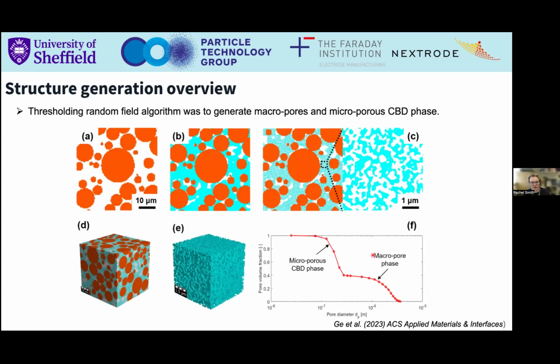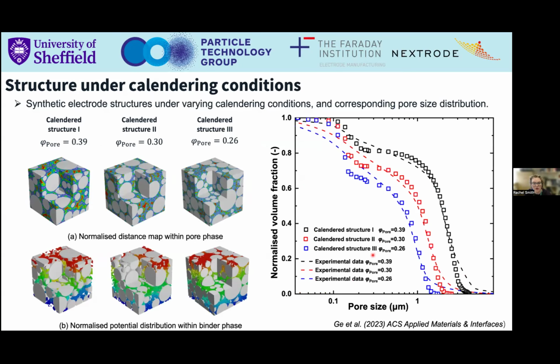And so we came up with an idea, rather than when we try to do our electrochemical simulation, we should look at how important are these micropores to the performance of the electrodes. And of course, we can do that digitally because we can use algorithms to create these micropores of the CBD structure inside the electrode, and we can change the relative amounts of micro and macropores while keeping the total porosity the same. So we have that power with the computer. So we looked at